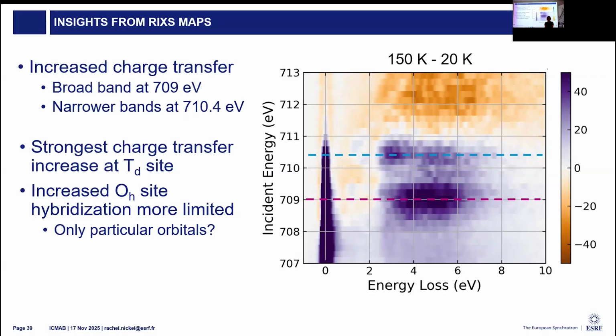Absolutely. So the direction of the charge transfer, whether it's positive or negative, we have the measurements, we have the analysis, and at 100 Kelvin, this fluorescence line that was remarked on before, why there's no clear Raman-like excitations, that turns off at 100 Kelvin, and we can see that this fluorescence band extends all the way to the elastic line. And so there is no band gap, and that tells us that the high temperature state is most likely negative charge transfer.